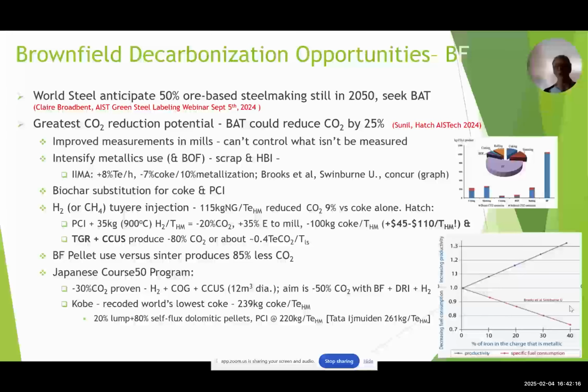If we intensify scrap and HBI use, we can increase productivity and reduce coke. And it's shown by IIMA that 7% coke is available for every 10% metallization. And Brooks et al. at Swinburne concur, as you can see from the graph down here at the bottom. Biochar substitution for coke and PCI is limited for the coke, as we've already said, because it supports the bed in the furnace. Hydrogen or natural gas injection into the tuyeres can reduce the coke by 9% alone.